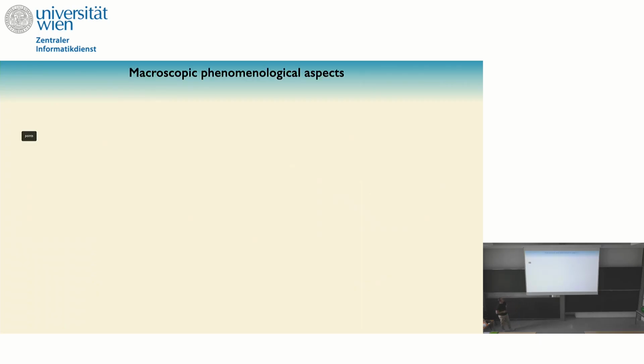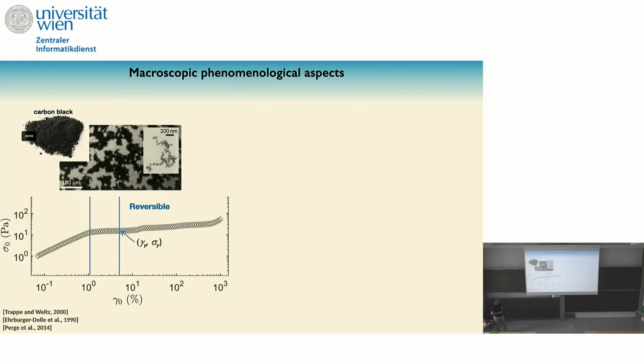Okay, so let's talk now about some macroscopic phenomenological aspects of this type of materials. Here I'm showing some examples of gels. I'm going to start with carbon black gels. Here you have a nice microscopic picture of these carbon black particles that are suspended in the fluid. They form this interconnected sparse network. And then if you do a startup shear experiment where you apply the strain and you measure the stress, you can plot the stress as a function of the strain. And what you see is that you have a fairly linear regime, then some nonlinear regime with these two peaks that I think Simon talked about yesterday, this double yielding. But let's say that the yielding is here, and then the system eventually flows.